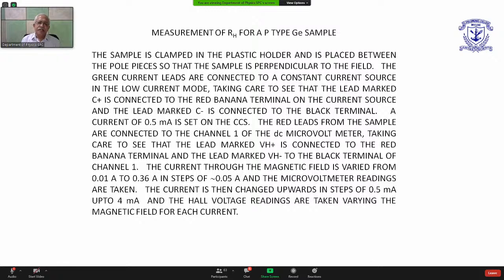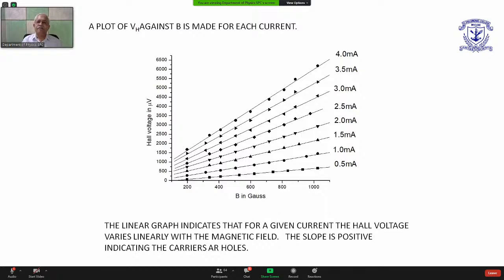Now we vary the current on the electromagnet from something like 0.01 ampere to about 0.36 amperes in steps of something like 50 milliamperes, and keep recording the readings of the voltmeter at different currents. Once I know the current, one can compute the magnetic field for each current value which is set, and then we will have measured the Hall voltage. So therefore, we can plot the graphs.